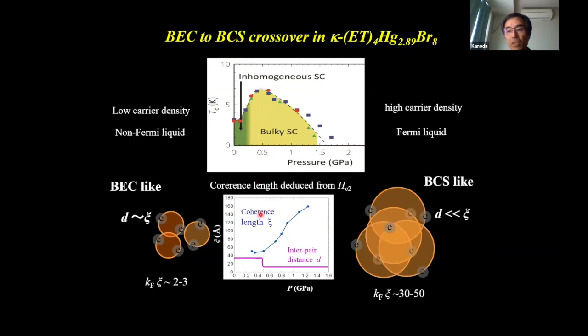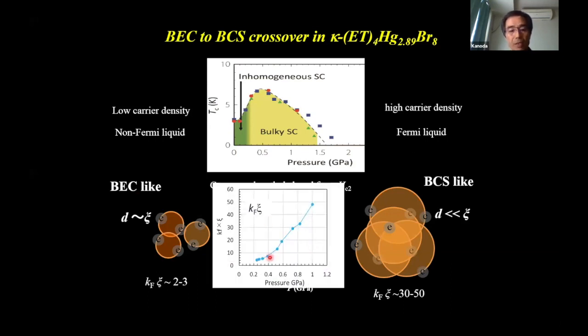By upper critical field measurements, we could extract the coherence lengths. This material shows a superconducting dome. This is the crossover, non-Fermi liquid to Fermi liquid crossover, here at high temperatures. And the coherence length is very short here. And the inter-pair distance of Cooper pairs is comparable. This means that this pairing is like a BEC. But in the high pressure regions, many Cooper pairs are overlapping. So BCS. So this is kF xi, where xi means coherence length. xi is of the order of unity, 1 or 2 or 3, in the low pressure regions. So BEC to BCS crossover occurs in this material.